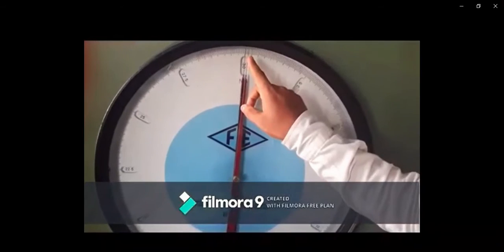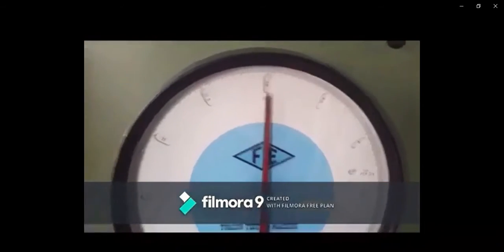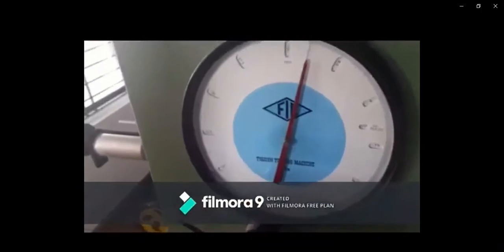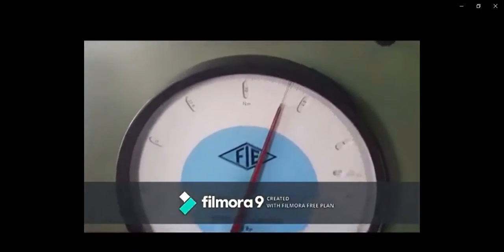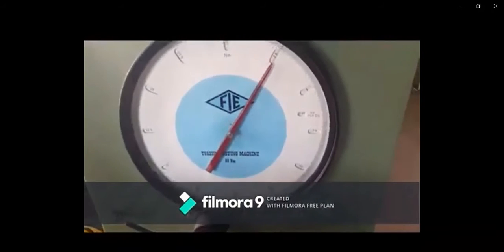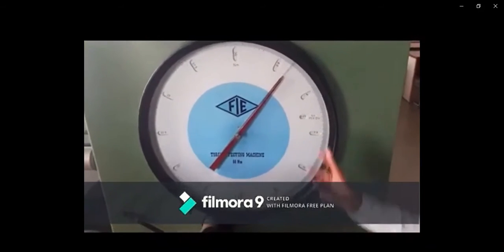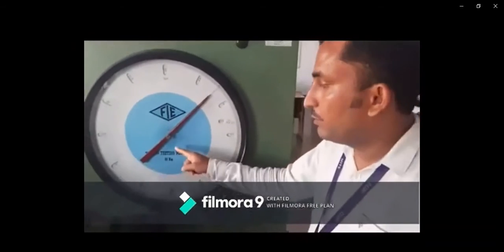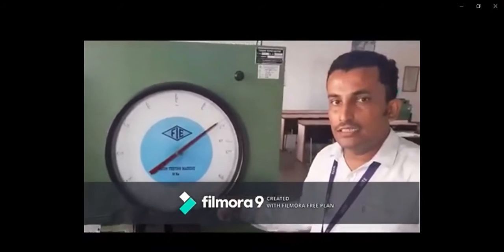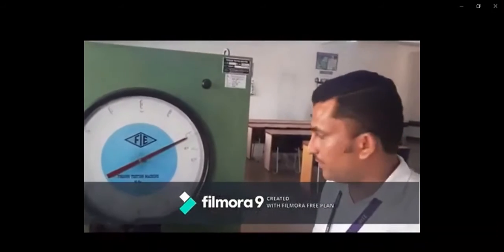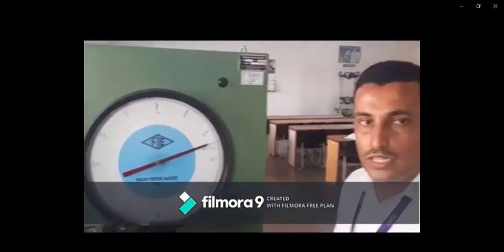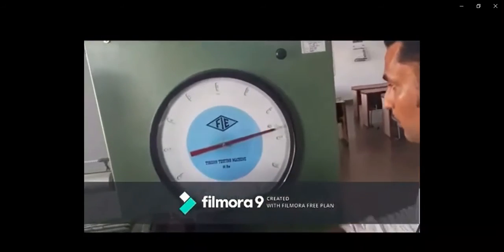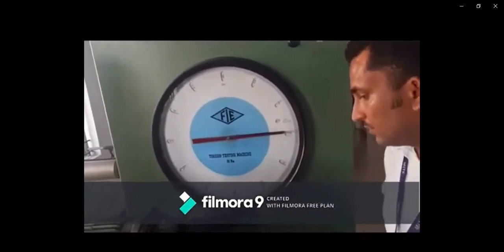Now the reading for 2 degree. Here we have 2 divisions. Each division carries 0.05. 2 divisions means it is 0.1 Newton meter. You continue like that, for every 2 degree reading you need to consider the torque. So once it reaches the yield point, the black needle will come back and the red needle will be stopped there. That reading will be taken as the yield strength or yield torque at the yield point. So that is very important for the calculation purpose. Keep on rotating and take the reading for every 2 degrees.